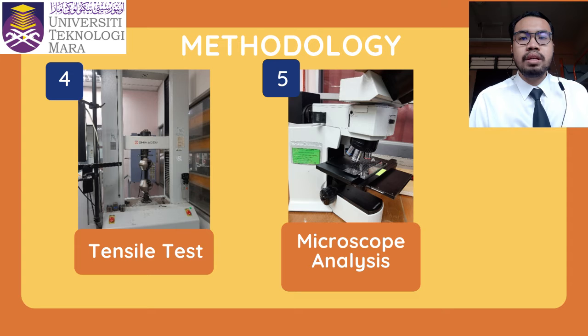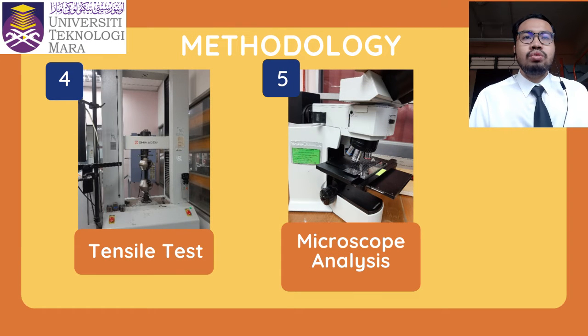After that, the sample must be tested using the tensile strength test. To accommodate the length of the test sample, place the lower and upper clamps in their respective positions. The sample should now be placed between the tension clamps. From the highest clamp to the lower clamp, position the sample vertically. During the test, the alignment will guarantee that the specimen is not subjected to any side loading or bending. After fastening the extensometer, attach it to the length of the sample.